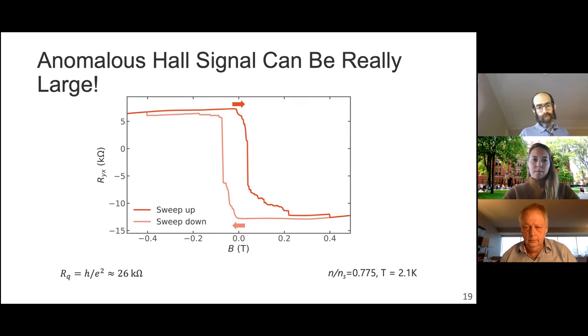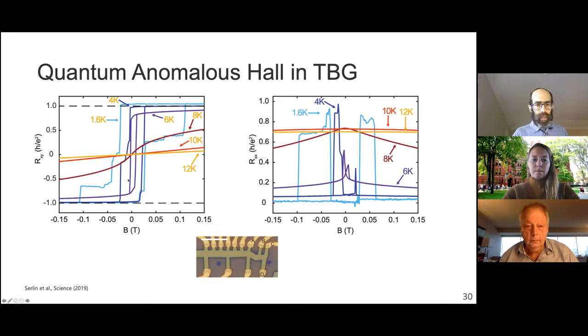And why is it not getting there? I think it's because there is some bulk conduction in the sample, whether that's because of domain structure or because the gap is not a hard gap. But I think that generally if sigma xx is not zero, then you will not find rho xy necessarily quantized. So that's my take on it. But if you look at Andrea Young's measurements, R_xy is actually very close to h over e squared, and they have to play some tricks because they don't have an ideal geometry. But I would say that it's not a quarter or a sixth. That's really h over e squared, and you can't see from this measurement, but it's really to around a percent quantization.